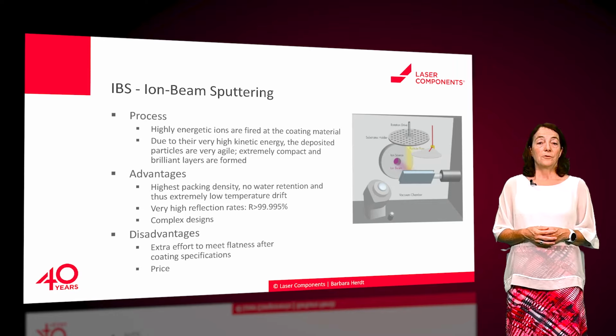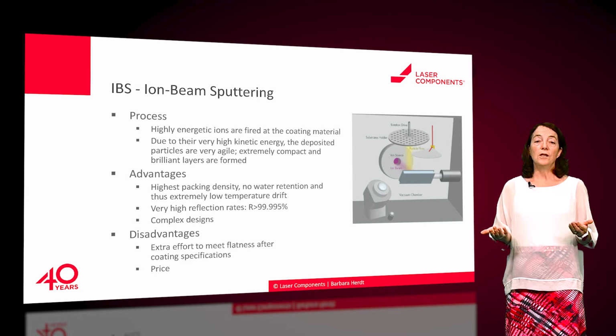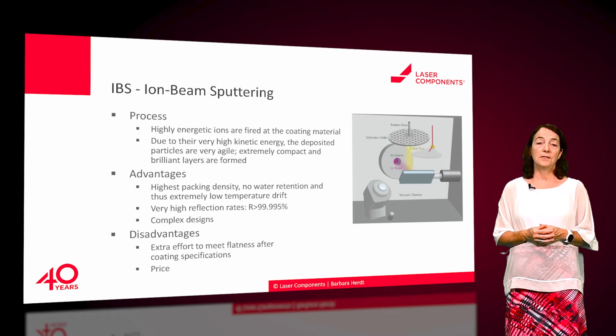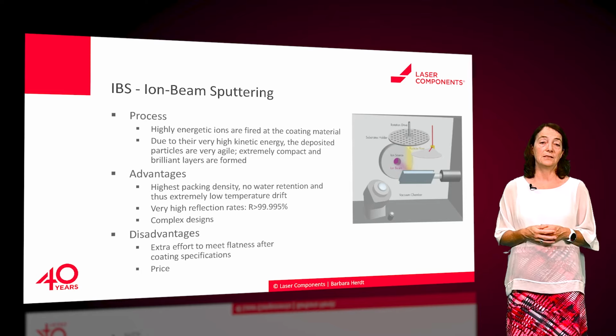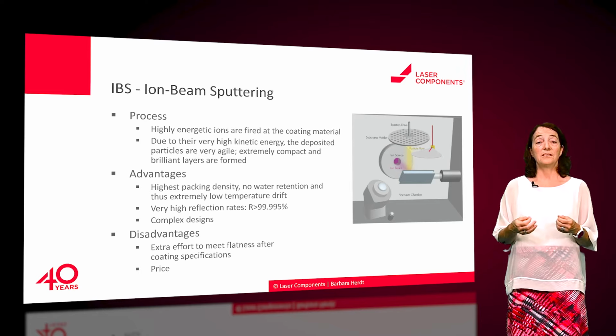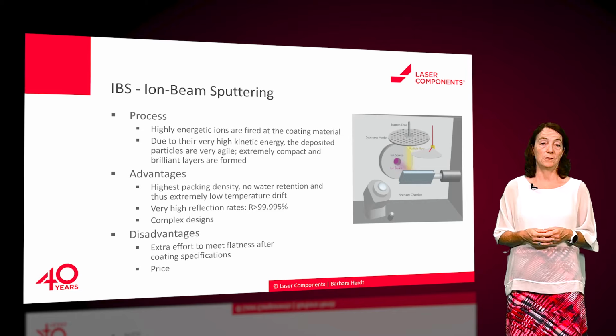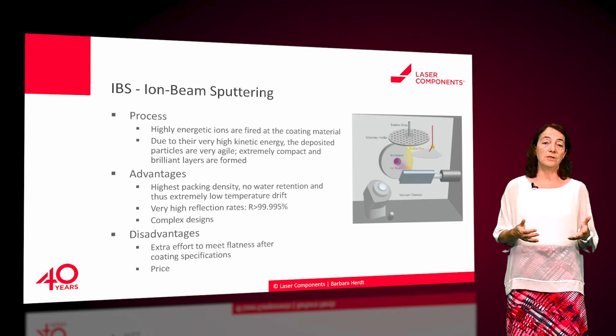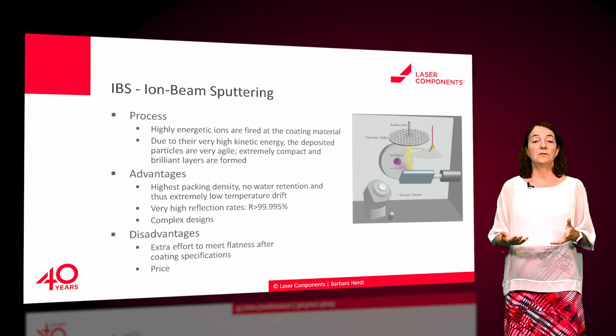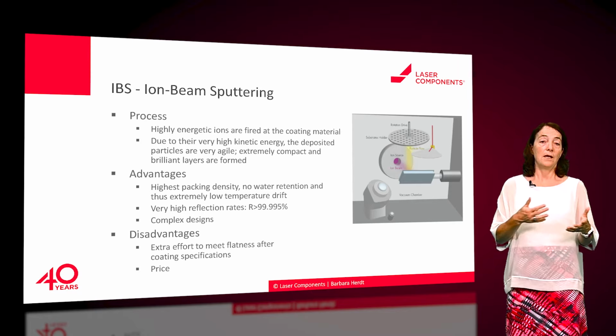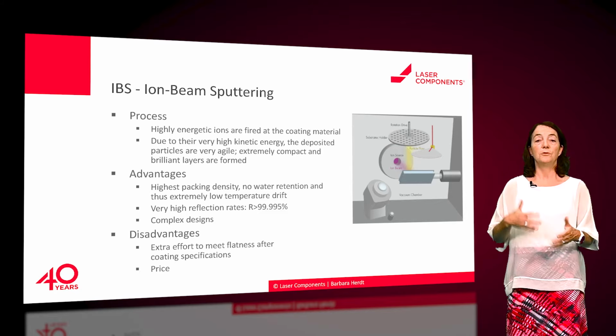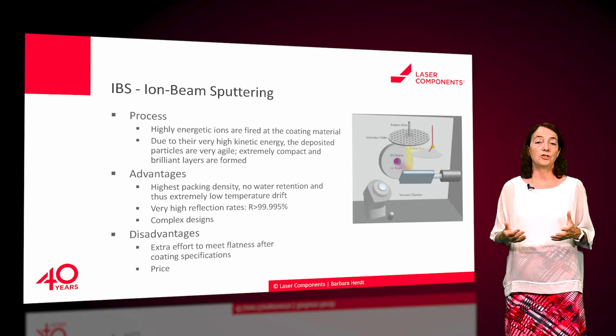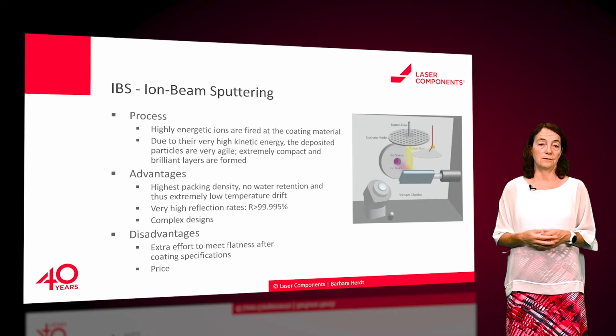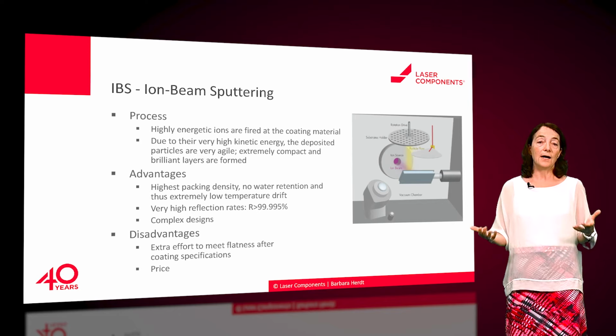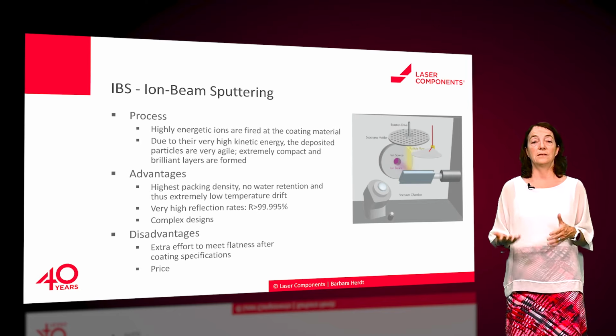As the material is coming from a rigid plate, there is nearly no limit on coating material, and high reflectivities in very complex coating designs can be done. But the sputtering is a much slower process. If you do the same standard coating with E-beam and IBS, the IBS will take about double as long. But by the way, IAD will be in between IBS and E-beam. Some of the coatings we do for high power laser application take more than 48 hours. So price is always higher for IBS than for E-beam and ion-assisted deposition.